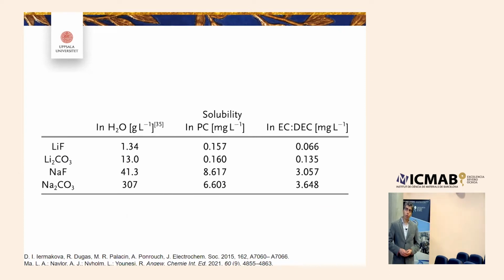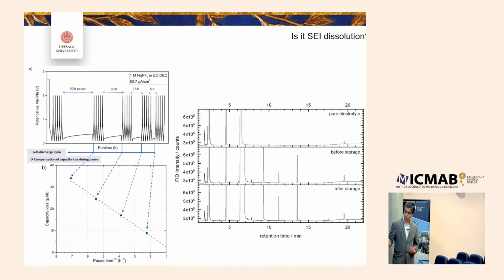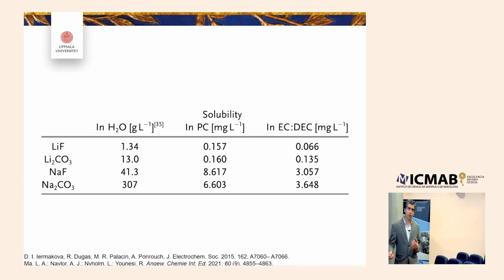We also tried to do ICP to understand how much SEI species we can dissolve in the liquid electrolyte. The problem is that if you look at real electrolyte, there are so many peaks—it's extremely difficult to see what these species are. That is the challenge, but we can imagine some of the species, as many literatures have shown.